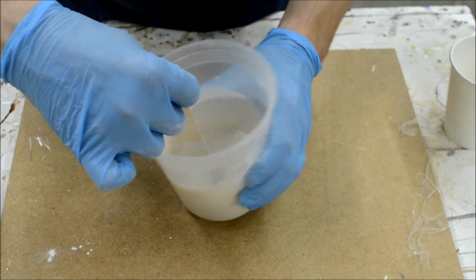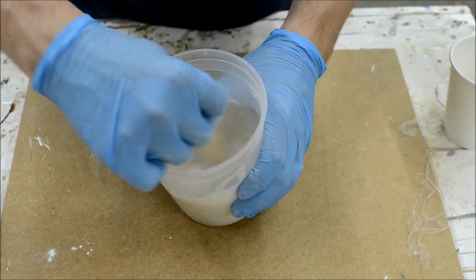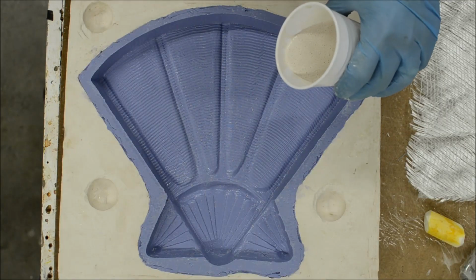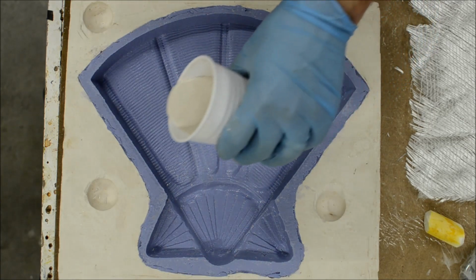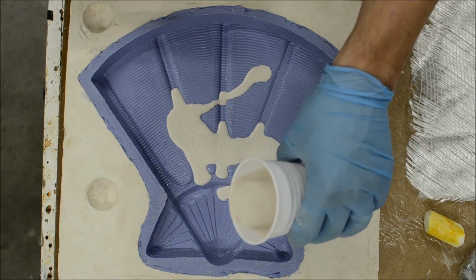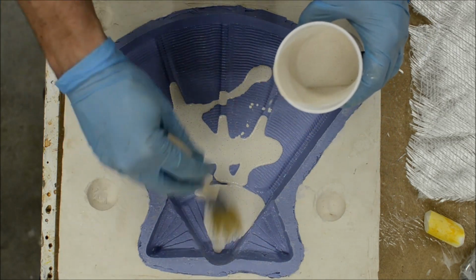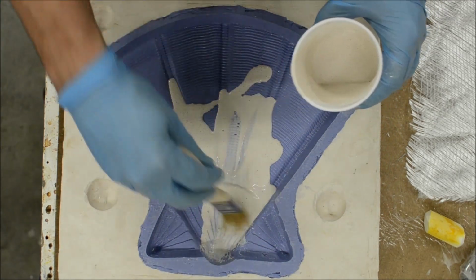To use aqua resin, you combine a liquid and solid component. For fiberglass work, one part liquid to two parts powder is sufficient. Aqua resin can be thickened simply by increasing the proportion of powder to liquid.